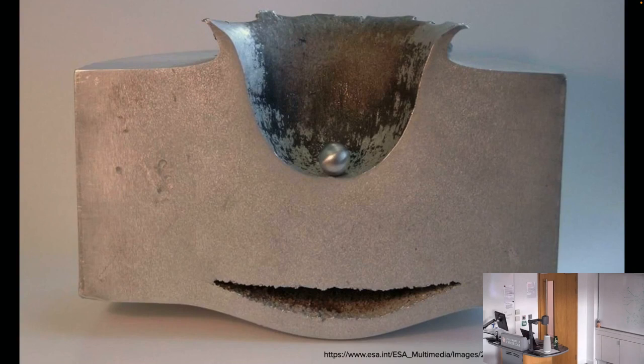And you can see, of course, this giant crater that forms, sort of like you would expect. But there's also this failure feature down here. Right? That is indicative of what we call spall. And it's associated with a tensile failure mode in this material, even though, of course, the impact of the sphere on the surface creates a compressive shock wave. And I'll describe for a second how that happens.